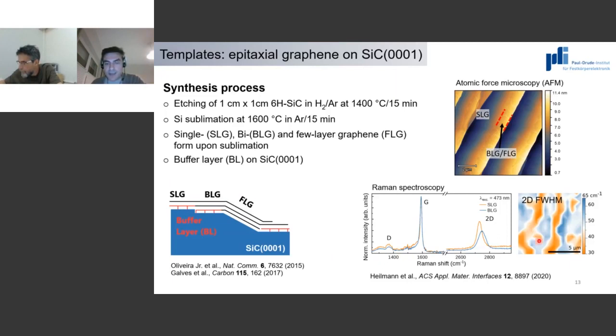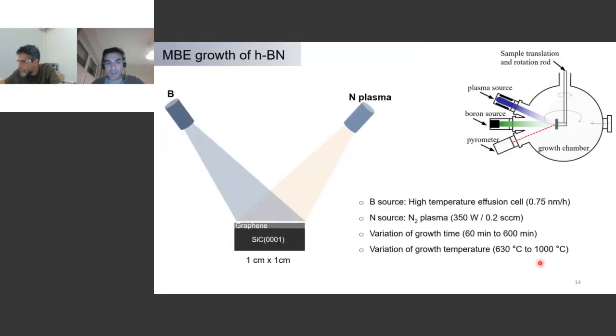And we have studied this type of substrate now for many years, and you can use Raman spectroscopy, for instance, to get information about the number of layers that you have close to step edges, like bilayer graphene and so on, while on the terraces you have single layer graphene. This can be seen, for instance, by Raman mapping, where the full width at half maximum of your 2D peak is a kind of fingerprint for graphene, and you can then get information about what kind of graphene you have there.